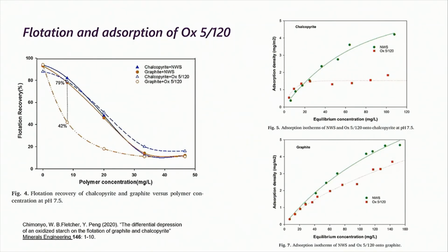And just quickly, the types of adsorption isotherms that we're able to establish with that. See up the top there, the chalcopyrite, and the bottom, the carbon, or graphite. The response for both is quite similar for the native wheat starch, and that fits in with what's on the left there. But you're seeing quite a different adsorption isotherm using the oxidized starch, where a greater weight of oxidized starch is adsorbing to the graphite rather than the chalcopyrite. And we're assuming that's underlying why there is some sort of shift in selectivity.